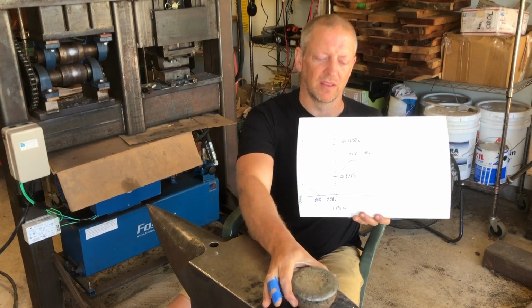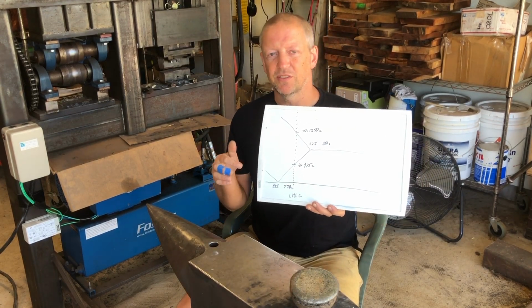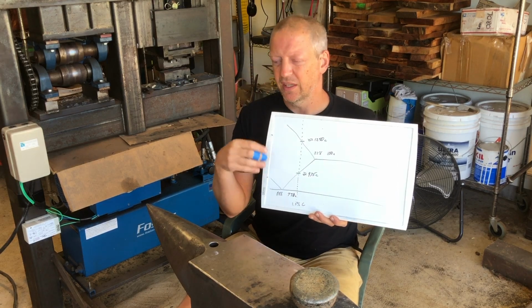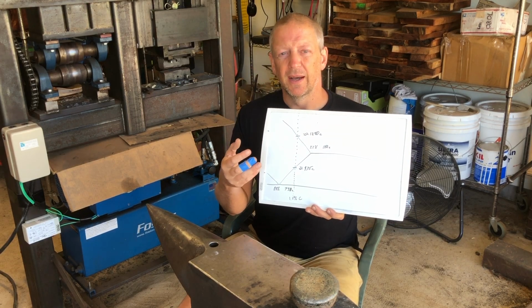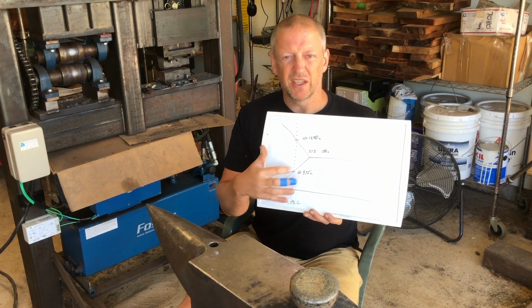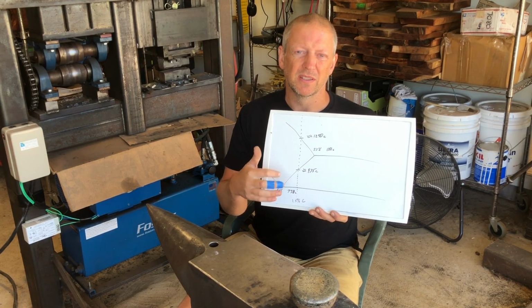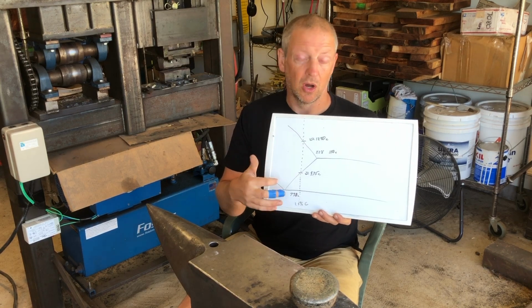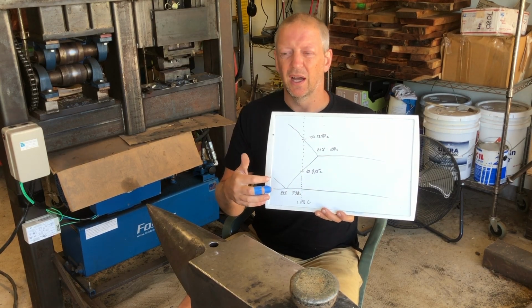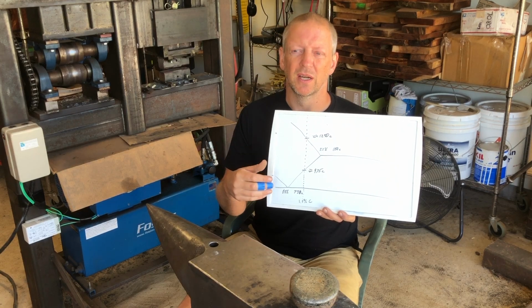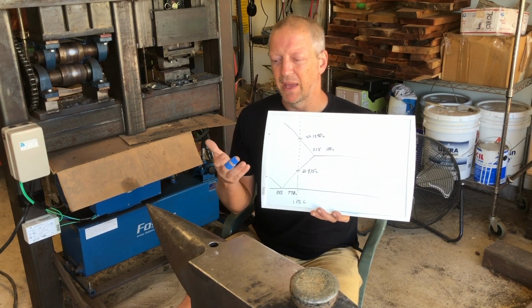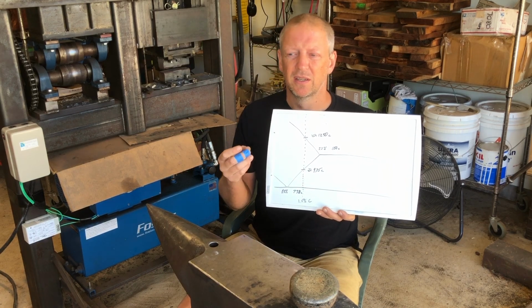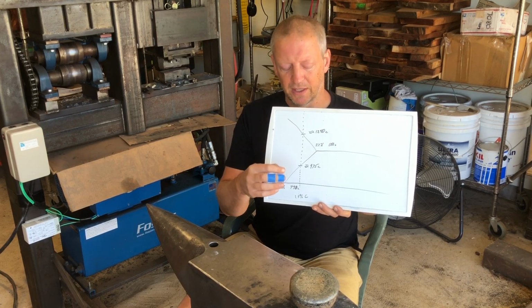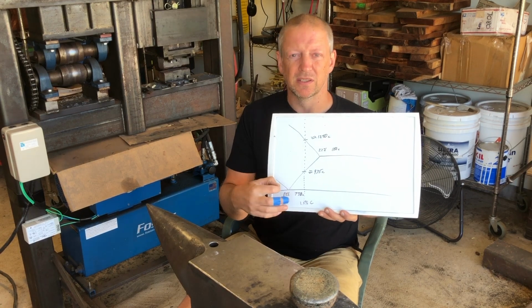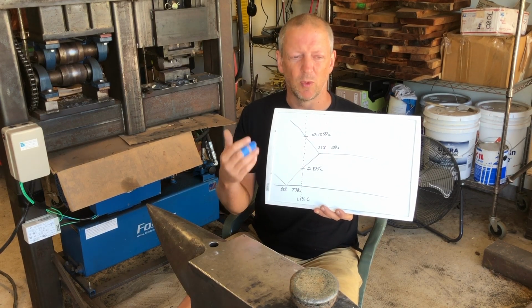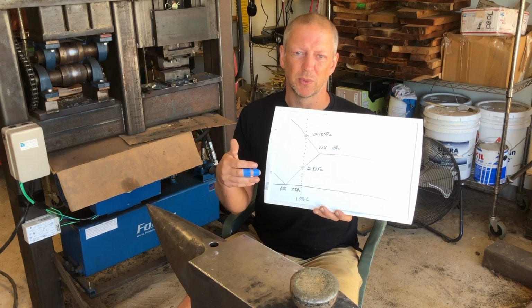Specifically not with an unforged ingot. And the reason for that is that the initial ingot is rather porous, and right in the same vicinity where carbides precipitate, so along or just below the ACM line, is also where graphite precipitates. If we look at historical blades, many of them actually have graphite in the blade, and that graphite essentially replaces carbides. And once it's in there, it's essentially impossible to get rid of.